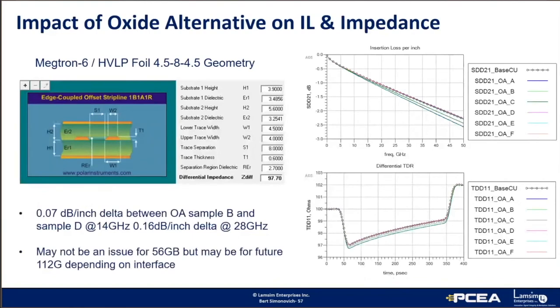Here I did a simulation study of a MEG 6 test geometry. The only thing I changed was the roughness parameters listed in the HD Pug study. As expected, the smoother the roughness shows improvement in the insertion loss, especially extending to 50 GHz. At 14 GHz, there's 0.07 dB per inch delta between sample B and sample D. At 28 GHz, this delta increases to 0.16 dB per inch. This suggests that for current 56 gig standards, the etch oxide alternatives are probably not that much of an issue, as long as the etch treatment is tightly controlled by the PCB fabricator. But for future 112 gigabit system standards, it could be an issue.